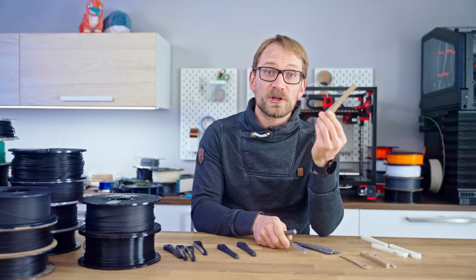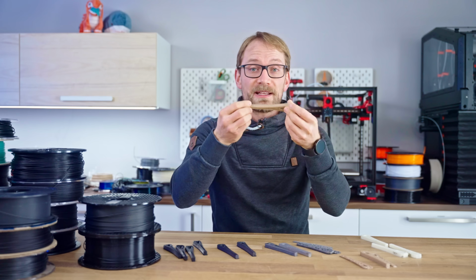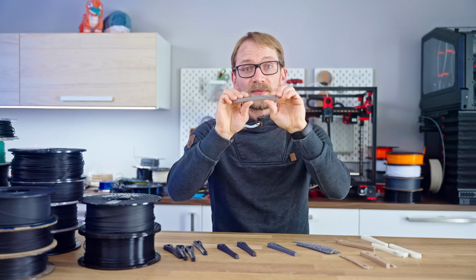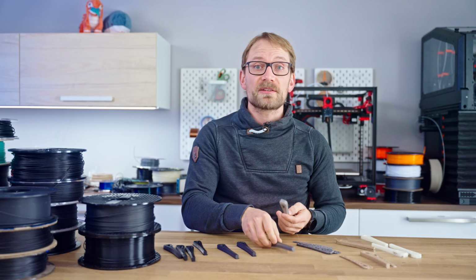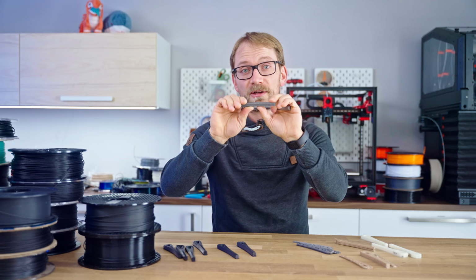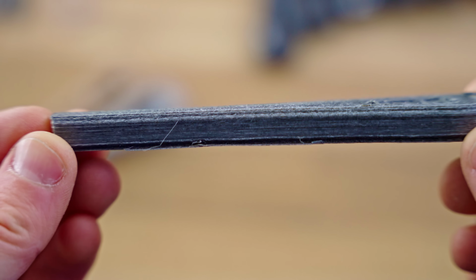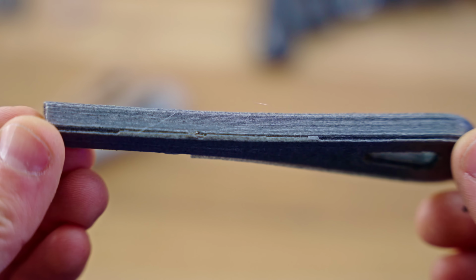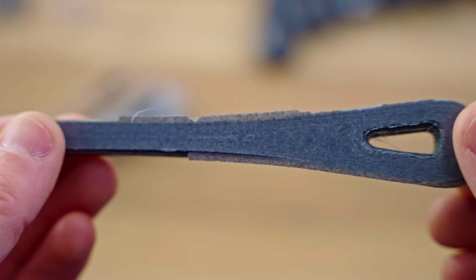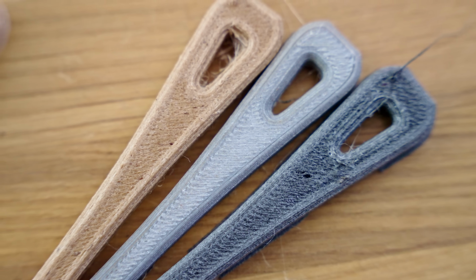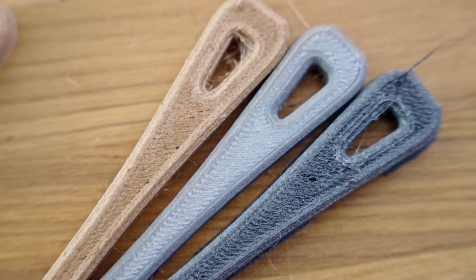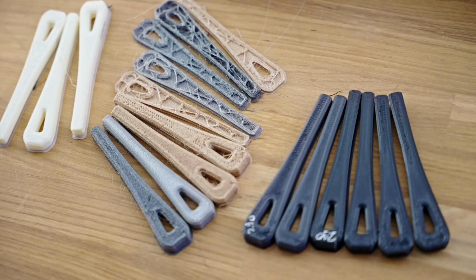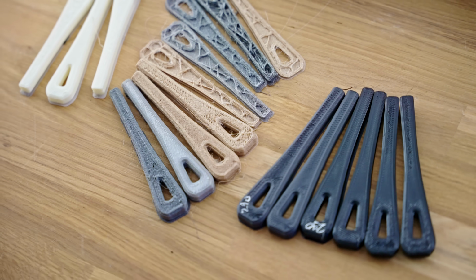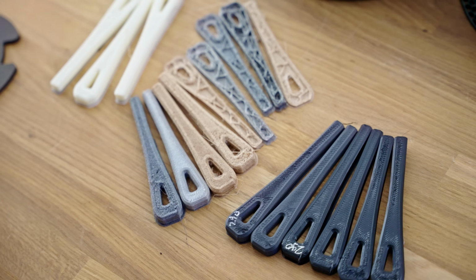The wood dust print actually is noticeably softer, as is the carbon dust print. The part with about 15% of the properly sized carbon fiber particles mixed in feels about the same as the part with nothing at all added in. And I think any benefit that the carbon was adding is being eaten up by the less consistent filament diameter, so the part ends up with under-extruded bits here and there.